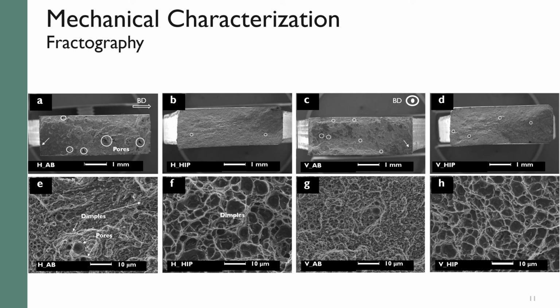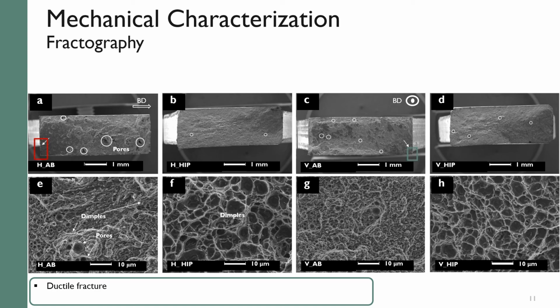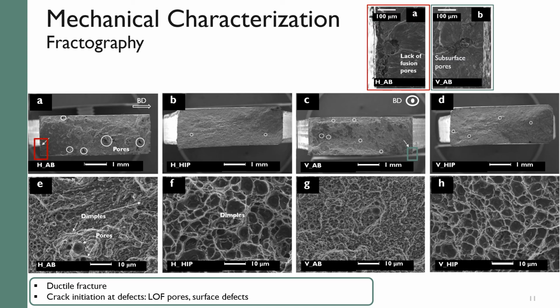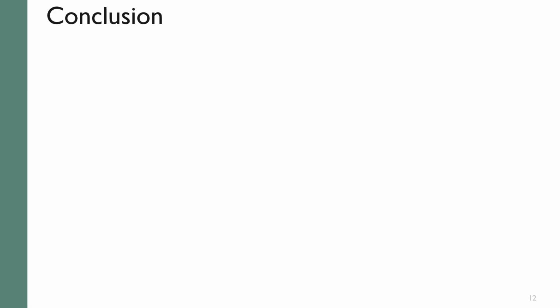Finally, fractographs of as-built and HIP samples are shown here, and the crack initiation sites are marked in white in figures A and C. As-built samples have more pores visible at the fractured surfaces, while dimples suggesting ductile fracture are observed in all samples in the pictures below. When we have a closer look at the as-built samples, we can see that lack of fusion pores or subsurface pores acted as crack initiation points.